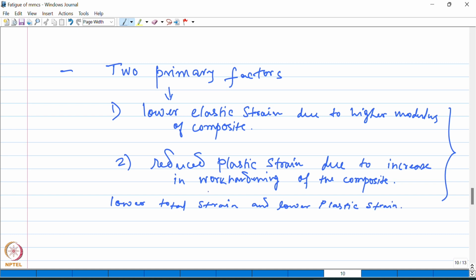This basically results in a delayed crack initiation, and as a result of that, the number of cycles to failure will be much higher, resulting in a better fatigue resistance.